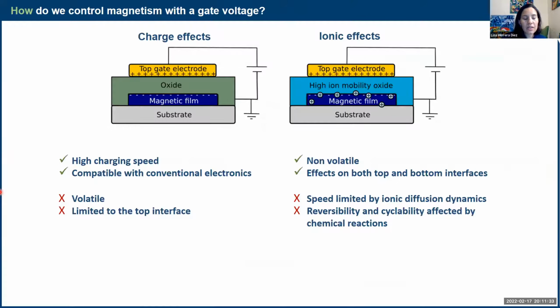So let me tell you how we can control magnetism with a voltage. You mainly have two options for this. On the left are the charge effects. This is the typical field effect transistor structure that you know from all types of applications. You have your magnetic film, which is one of the electrodes, an oxide and a top electrode, and you apply a voltage, and this generates a charge accumulation at the surface of, in this case, your magnetic film. This has a number of advantages: it's electronic, so it has a high charging speed, basically instantaneous. And it's very much compatible with conventional electronics and nanofabrication. So this is very much in benefit of applications.